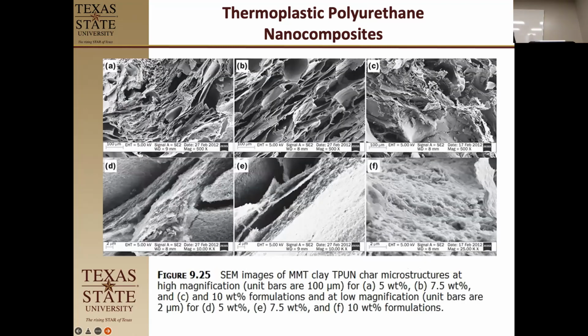Okay, so once you ablate it, what does it look like? So we have the top one here, looking at the char level as we increase the amount of montmorillonite from 5 to 7.5 to 10 right here. And we'll see that it has kind of a weird texture to it, but notice it has porosity, it has surface texture. It started as a smooth plastic surface, and now what is probably being left behind is montmorillonite bound by carbonized polymer system. And then if we look at the lower magnification, we look at the different surface roughnesses here. We see the surface roughness texture as it's ablating down. It's just like the polymer is burning out from below the montmorillonite. It's just kind of collapsing.